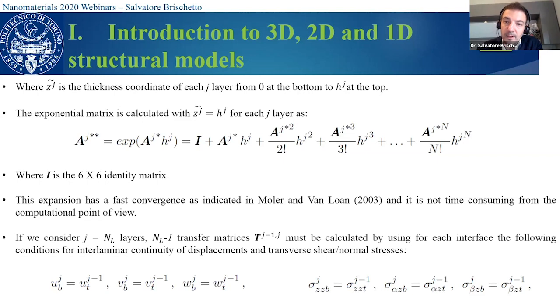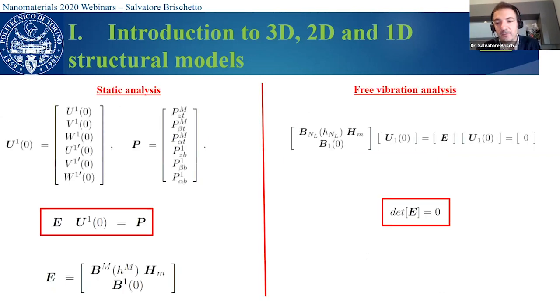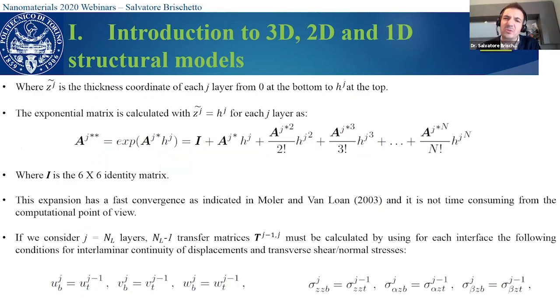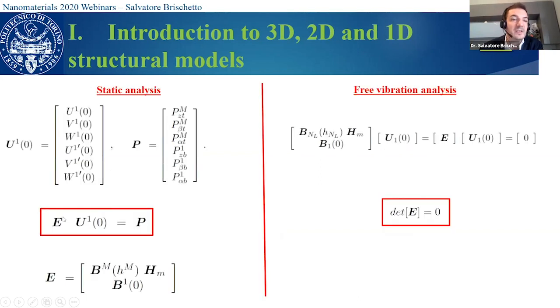Okay. After this, we have a layer-wise model, but this layer-wise model is very, very important. One consideration: it is not very heavy from the computational point of view, because even if we use a layer-wise approach, first of all, the convergence of this expansion is very, very fast, and moreover, even if we impose the continuity by means of these transfer matrices, finally we always obtain a final matrix which is always 6 by 6, independently of the order of expansion for the exponential matrix method and the employed number of mathematical layers.